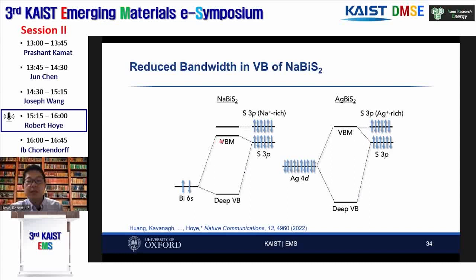Whereas in the silver-based compounds, it's the silver that dominates interactions with the sulfur. Because they're closer in energy, we have a much wider splitting, and therefore a much wider distribution of states in the upper valence band. And therefore, we have a lower absorption coefficient in the silver-based compound.